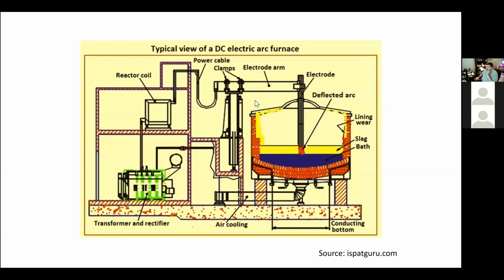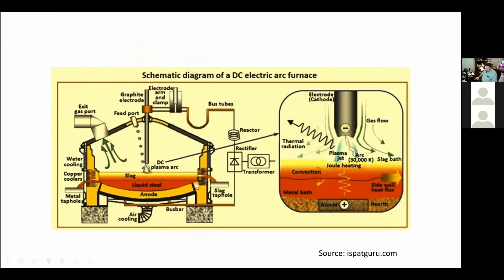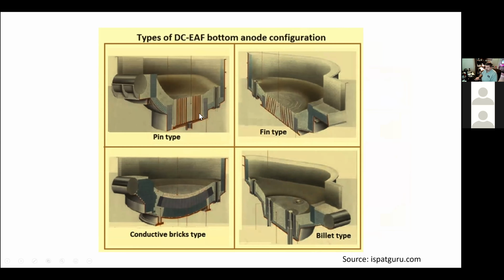This just shows a DC furnace. In a DC furnace, you have a single graphite electrode and the conductive path back, the return anode, is actually in the bottom of the furnace. And that can consist of steel pins, or steel fins. It can consist of conductive refractory, a carbon-based refractory. So there are a number of different types of DC furnace return anode bottoms that are in use.